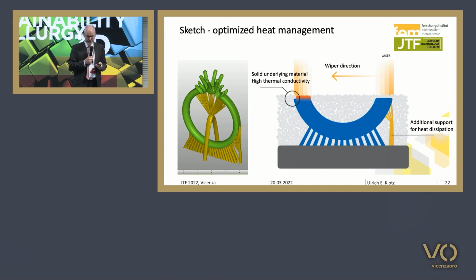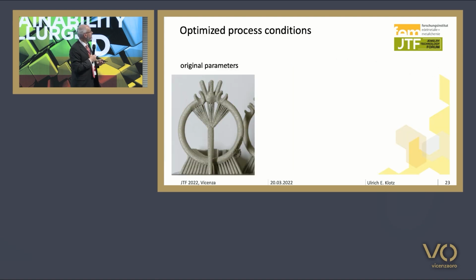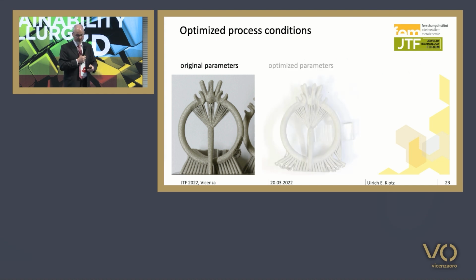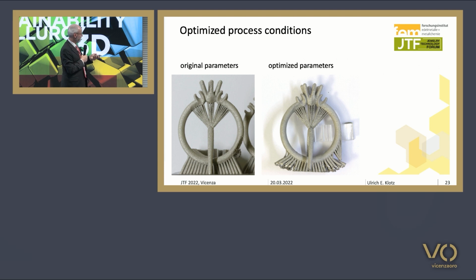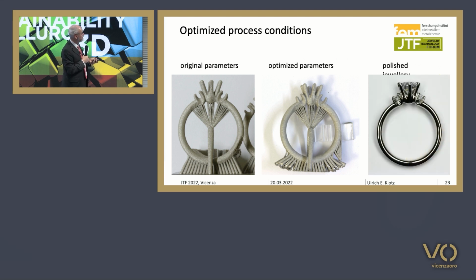So we applied such supports, and this was the original parameter with the defect here. Then we used the new supports. You can see them here, and this could fully avoid the problem of the overheating on this side of the ring.